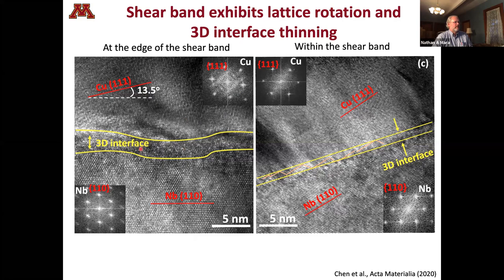Copper starts to rotate right at the edge of the shear band. So here's copper in the edge of the shear band. Niobium is outside. So the planes of copper have started to rotate. Niobium is still pretty static. And as you move inside the shear band, both of these phases now start to co-rotate, they become coincident, and we see that the 3D interface also rotates.